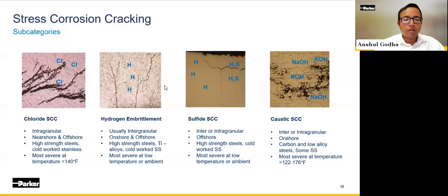Okay, so first off, there are a lot of agreements as well as disagreements within the literature about what is the exact mechanism for each of these forms of corrosion. One of the major ways of distinguishing between the different forms of corrosion is by looking at how the crack propagates and appears in the microstructure once we mount the sample and etch it using the right etchants. If the crack is intragranular, in other words, if the crack is cutting across the grains, it is typically a very strong indicator that you're dealing with chloride stress corrosion cracking.